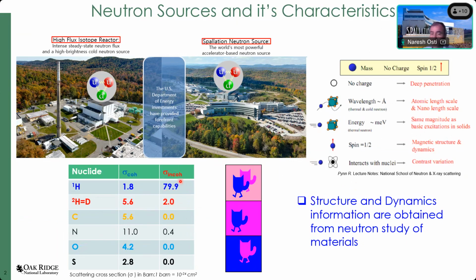Using this contrast in the scattering length density, we can bring variation in the scattering length density of the material in order to probe the system of interest. You can play with the hydrogen and the deuterium to make only one object visible, and you can play with them to make another object visible. You can also play with them to make both objects visible in the material. It means that it allows you to selectively mask a certain portion of the material so that you can get the information from another portion of the material. That's why this is the unique capability of the neutron, which you do not get in other techniques. Therefore, we use this technique to resolve the structure and dynamics in material.